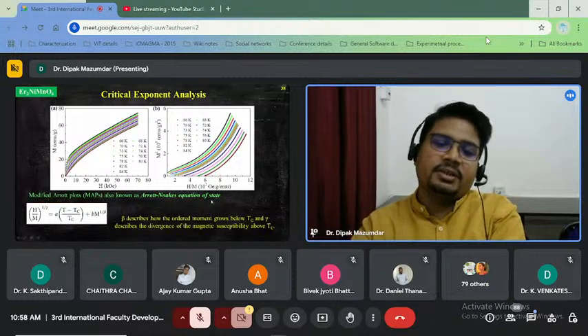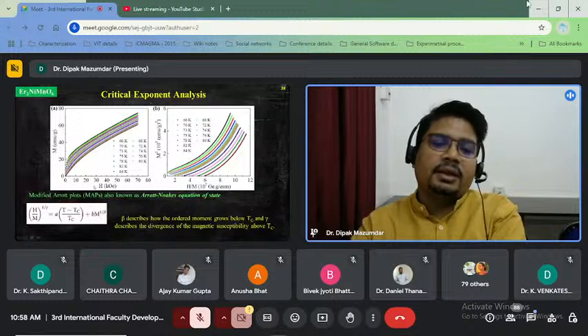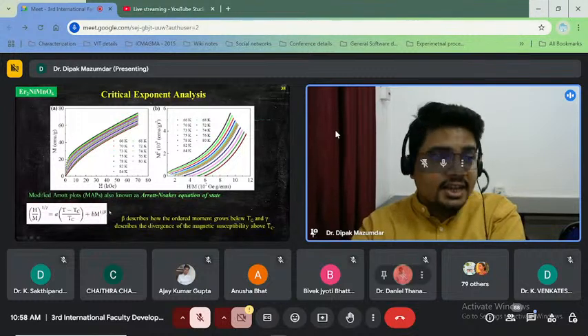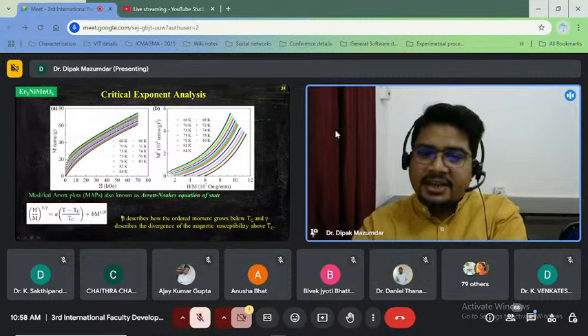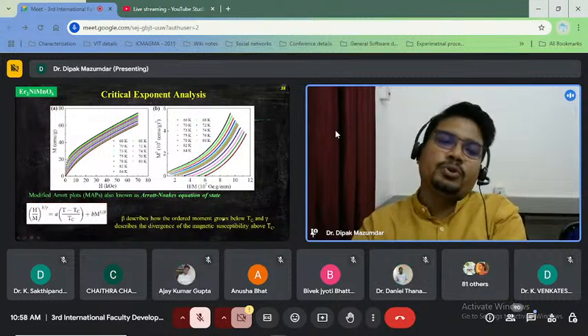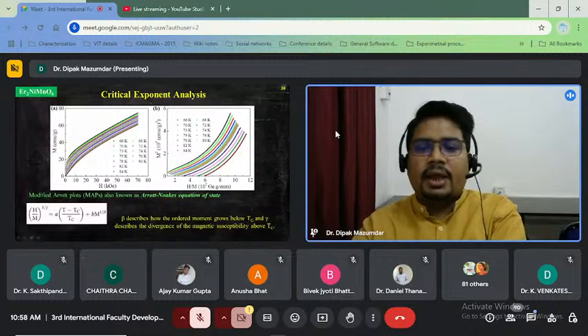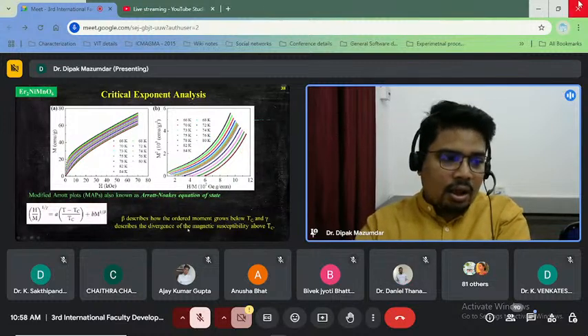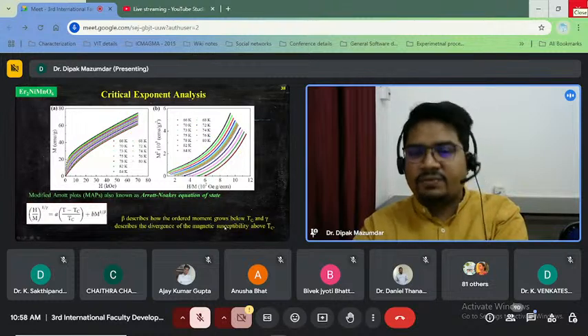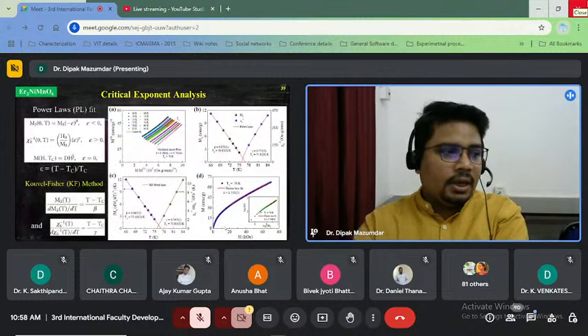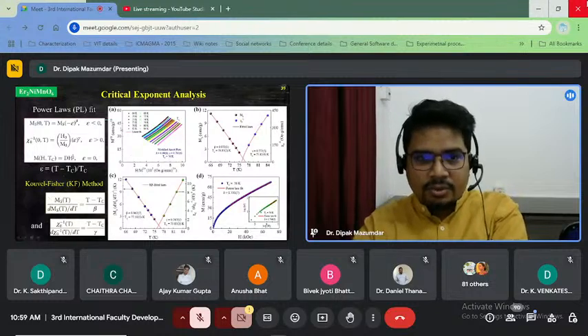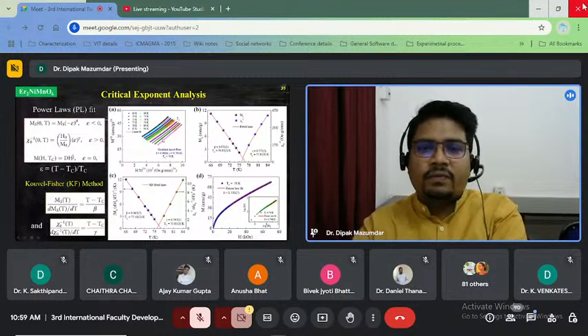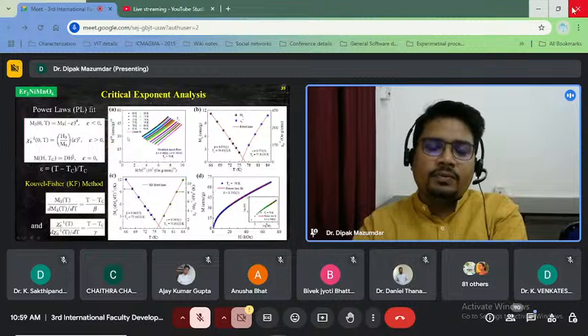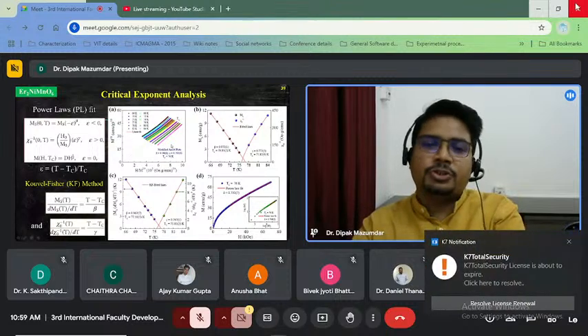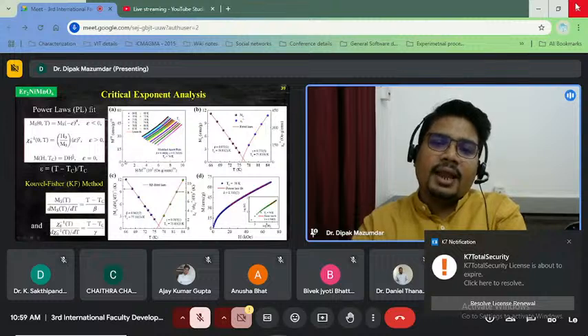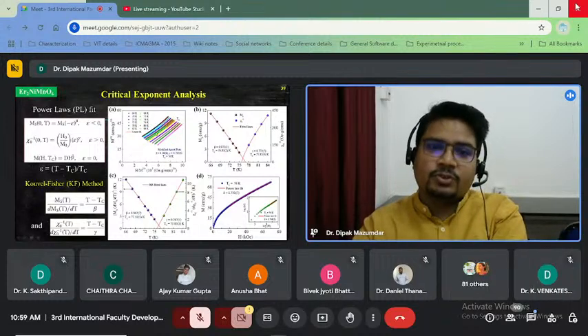And for critical exponent analysis, I am taking some magnetic isotherms near my TC region, and by using the modified Arrott equation of state given by this equation, we can determine the values of critical exponents beta and gamma, where beta describes how the ordered magnetic moments grow below TC, and gamma describes the divergence of the magnetic susceptibility above TC. And after getting the fitting, we have calculated the values of beta and gamma according to the Arrott equation of state. The line which is close to TC will pass through the origin.